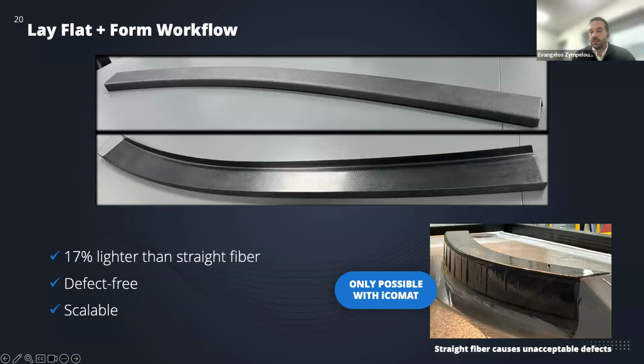Now, if you try the same workflow with a straight fiber preform, everything is the same. Material, forming system, mold, everything the same. The only thing we change is instead of a fiber steer preform, we started with a QI preform. And this could be the result. It would be full of localized wrinkling and buckling, which are the defects I mentioned previously. So this workflow that you saw is really not possible today.